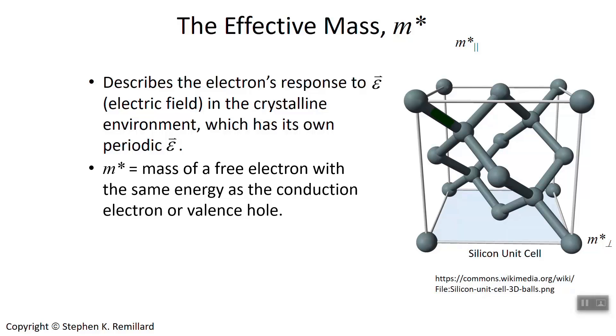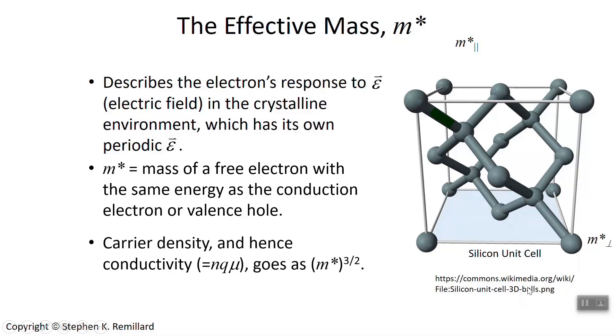So this varying acceleration, hence varying effective force, is accounted for not by actually calculating a position-dependent acceleration or a position-dependent force, but rather just by having a mass that appears to be the mass of the electron. If the electron were just a free electron in the environment of the crystal, m-star is the mass it would have. And if it's going in the blue plane, it's m-perpendicular-star. If it's going perpendicular to the blue plane, it's m-parallel-star, parallel to the axis. Any calculations that include mass actually use this effective mass, m-star.